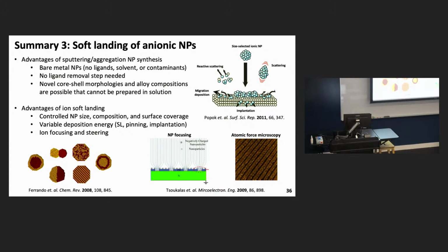So to summarize this section, there are a number of advantages to this gas aggregation and magnetron sputtering approach to synthesizing nanoparticles. The first is that they're bare nanoparticles. There's no ligands, solvent, or contaminants. And removing these things is typically a huge problem when you're doing research, particularly for catalysis, where you need that active surface site. We can make novel core shell morphologies and alloys that you cannot easily make in solution, including some of the structures shown down here.